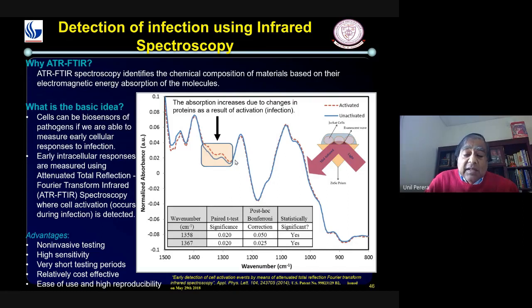So we did the infrared absorption. First, we did direct absorption going through, but we could not get any result out of that. So after that, we used what is called the ATR-FTIR, attenuated total reflection, because then we can control the penetration depth. You can control the penetration depth by adjusting the refractive index, wavelength, and the incident angle. So if you put a blood drop here onto the prism in the ATR crystal, so the prism is the ATR crystal.